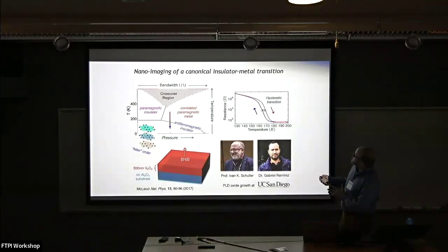As usual, you have an insulator-metal transition accompanied by orders of magnitude change in resistance. That's all nice and lovely. You can see a hysteresis, it's a first order transition. All that is very satisfying. We all wondered, why on earth is it the case that unlike a single crystal, this resistive transition is broad over 20, 30, even 40 degrees Kelvin? What did we do wrong when it came to growing the film? As it turns out, nothing. There's some physics there, which the real space imaging will actually show us.